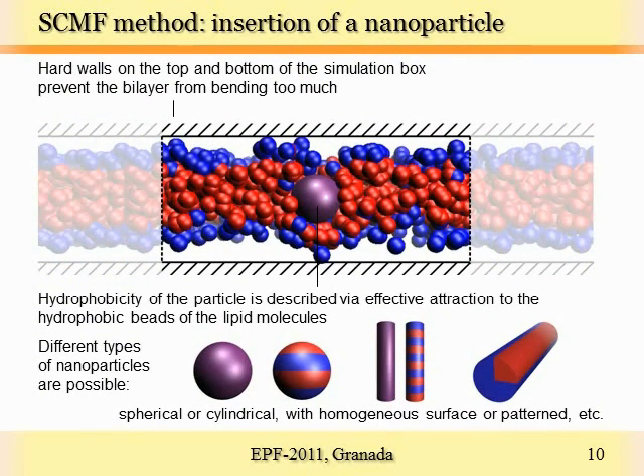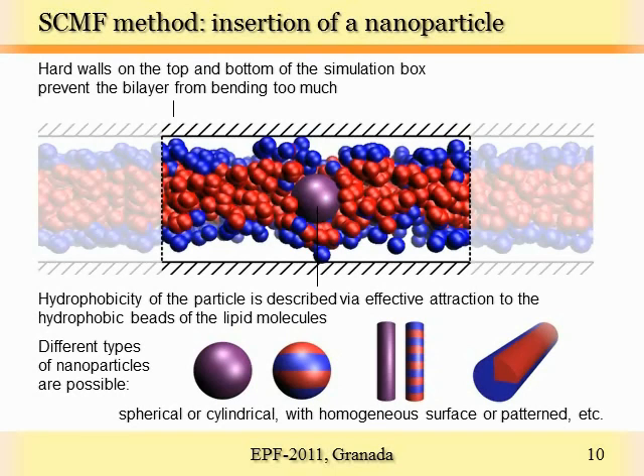As I mentioned in the beginning, we are going to simulate not only a pure phospholipid membrane, but its interaction with nanoparticles. To introduce nanoparticles into our model, we modify it a little bit: we add hard walls on the top and bottom of the simulation box to prevent bilayer bending. We then insert nanoparticles of specified shape and size in the simulation box and calculate the free energy cost of such insertion. By placing the nanoparticle in different positions in the box, we can calculate the free energy barrier for the translocation of the nanoparticle through the bilayer. We are working with cylindrical and spherical nanoparticles with homogeneous or patterned surfaces, but due to lack of time I will show just a few examples of the cylindrical ones.